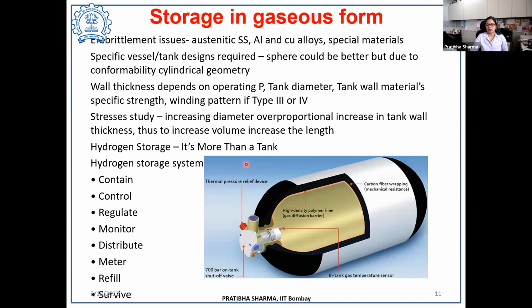Now, when we have to store it in gaseous form, the hydrogen is at a very high pressure. If we see the pressure in our household, let's say the pressure cooker, it is about 2 bar. And here the pressures at which we are storing hydrogen are 350 bar or 700 bar. So the material storing that hydrogen should have the strength to confine it at those pressures. Other than that, hydrogen has certain peculiar characteristics: it can react with different materials, and it can cause embrittlement, where metals exposed to hydrogen over a longer time lose their ductile nature and become brittle, and that can lead to failure.